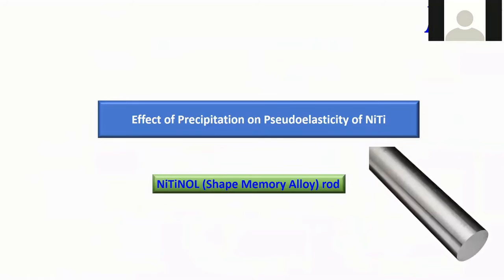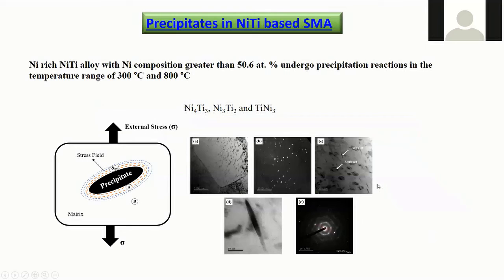So from there, we also looked into further details on the effect of different heat treatments. What we know for this alloy is that if we change the heat treatment, we are able to generate precipitates. And if these precipitates are generated, then that is supposed to influence the property in a big way. So we are again working on the same rod, and we know that this material itself is pseudoelastic on the bulk scale, but what happens microstructurally, on the local scale, is what is of our interest.